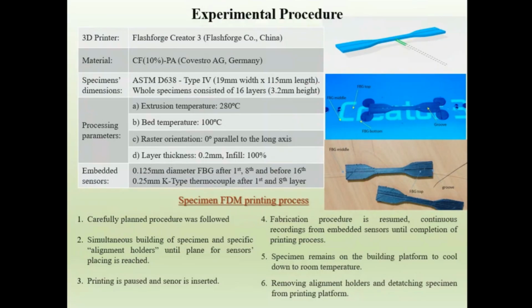So the specimen was curving and coming out, detaching from the building platform. So in a sense, we designed these Mickey Mouse ears, one layer, in order to make sure that it remained flat during the whole printing process. We also designed some grooves only on the gripping tabs, not on the specimen. We had fiber optic sensors placed one layer above the first one, in the middle of the specimen, on top of the eighth, and also one layer before the last layer built. At the same time, we incorporated a thermocouple in order to have simultaneous recording of the temperature developed during the building process.